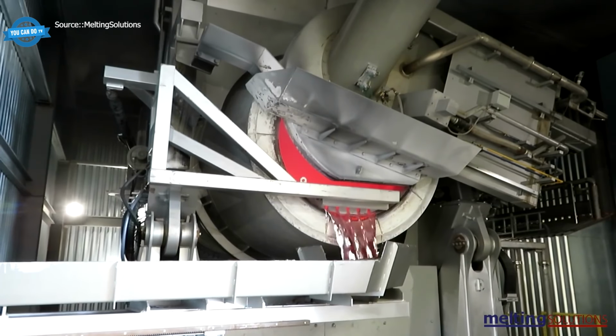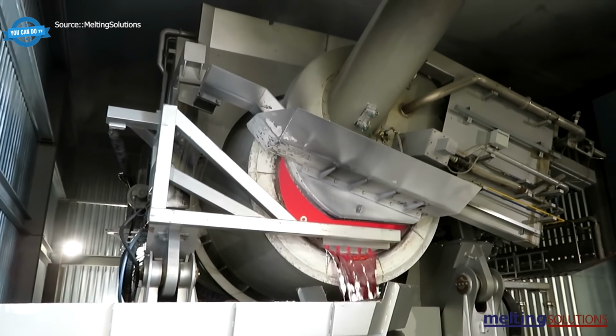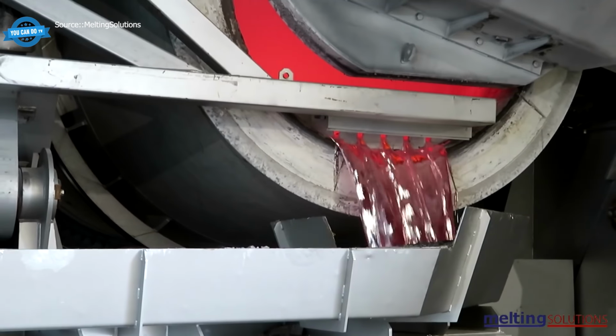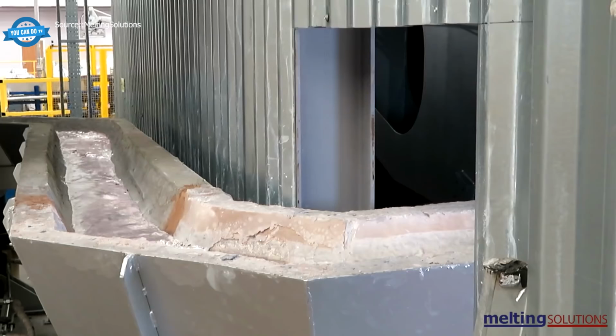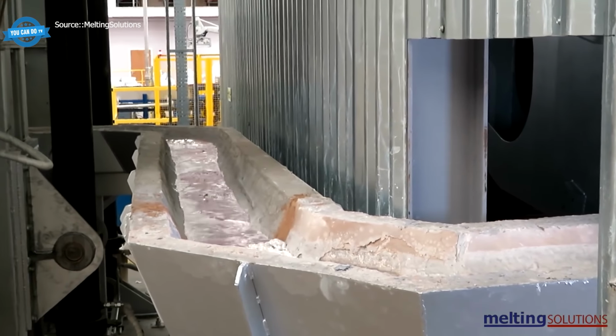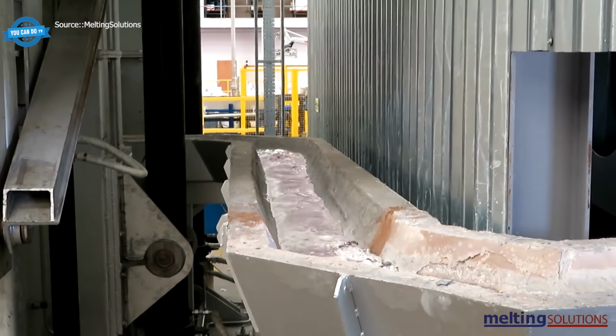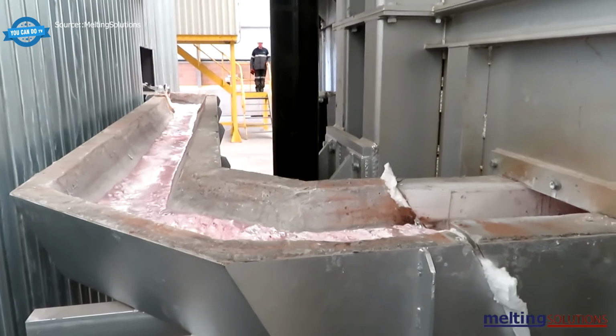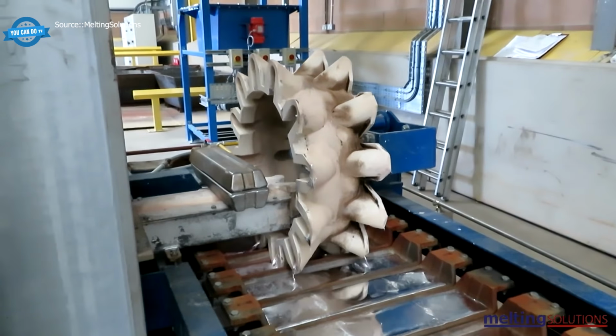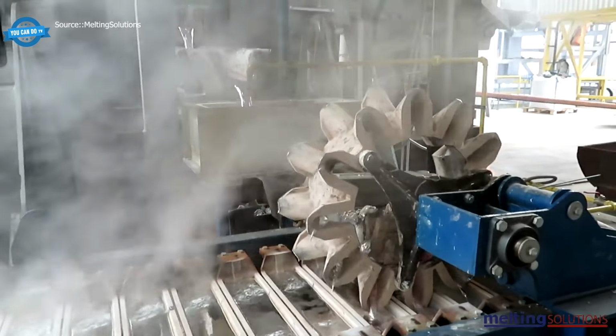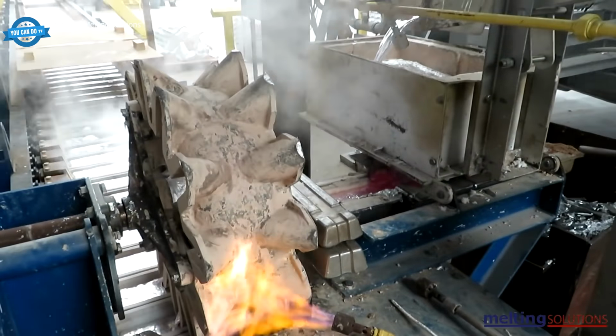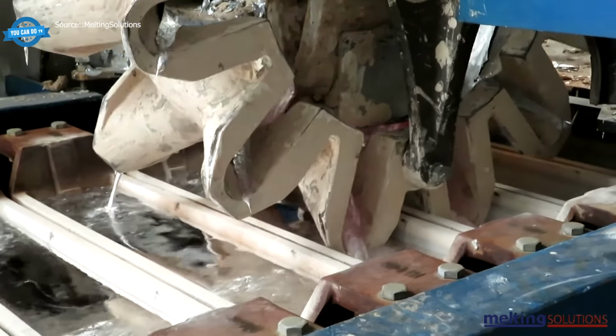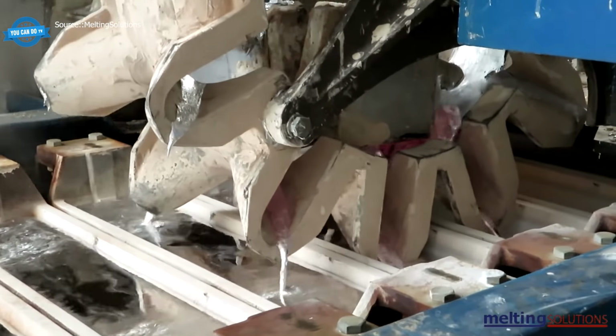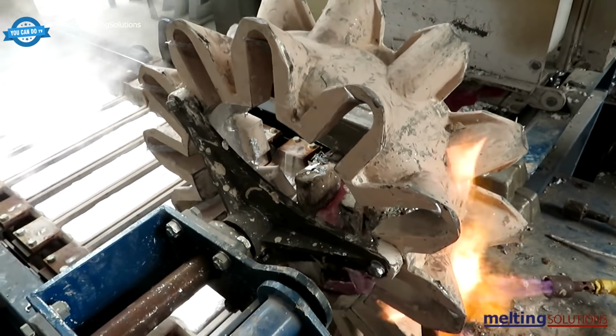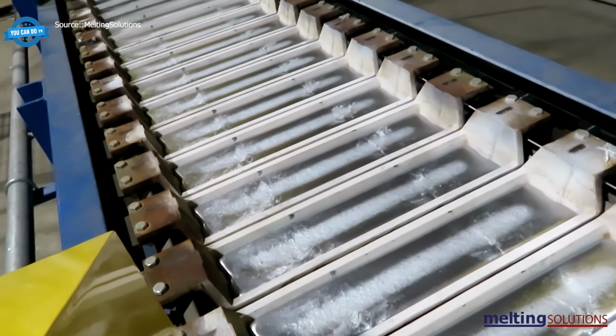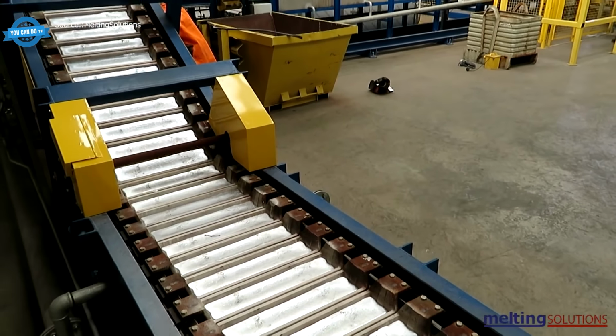Contamination, plastic, paint, oil, other alloys, burns off in the flames and gets captured by the emissions control system. The molten aluminum transfers to a 15-ton holding furnace with a porous plug for gas injection, which is where the chemistry gets adjusted before casting. Argon or nitrogen bubbles up through the plug, dragging dissolved hydrogen and oxide inclusions out of the melt. Skip this step, and every ingot cast from that furnace will have hydrogen porosity baked into it, and every downstream buyer will start asking uncomfortable questions.